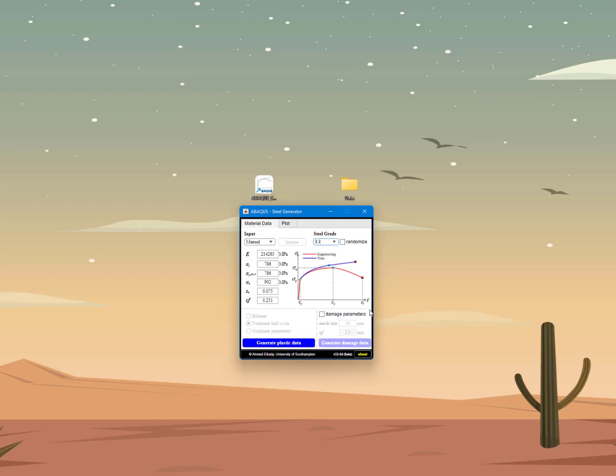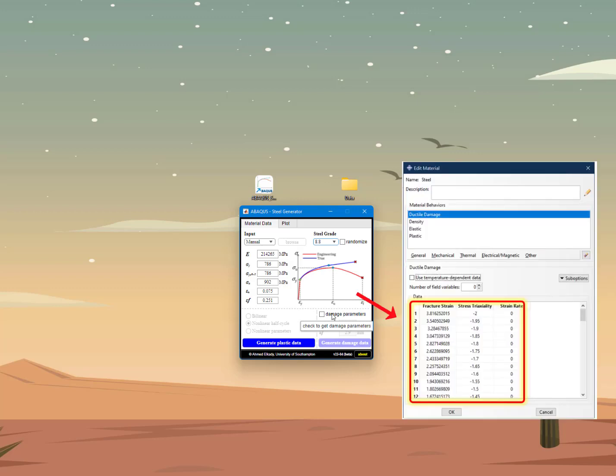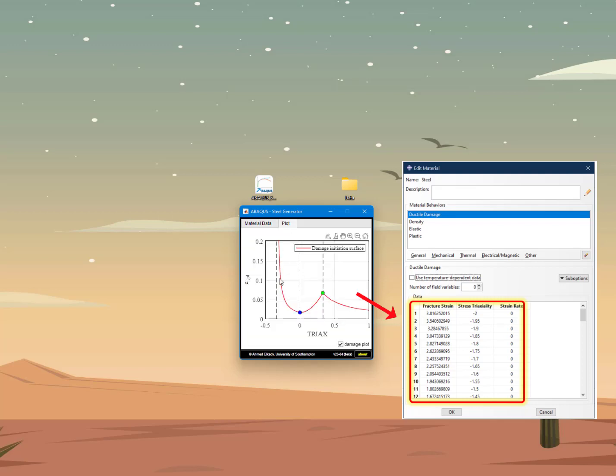There is another option that will not be available in the current release but will come in about two or three months. For the bolt grades specifically, you will be able to generate the ductile damage parameter for Abaqus. When defining ductile damage in Abaqus you need to define the plastic fracture strain versus triaxiality — that is what this part does. By specifying the mesh size you're using for your bolt and clicking 'Generate Damage Data', it will automatically generate the relation between plastic strain at failure versus triaxiality, also exported as a text file to copy and paste into Abaqus.